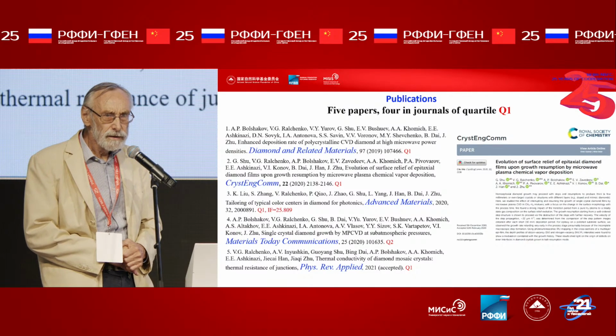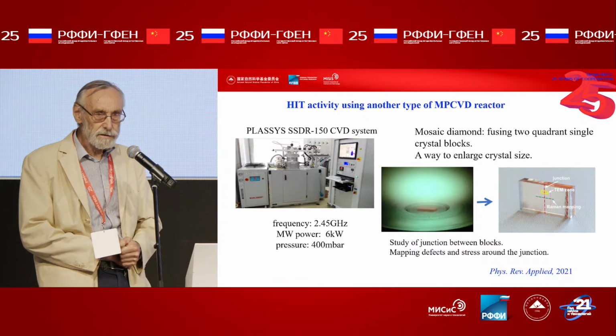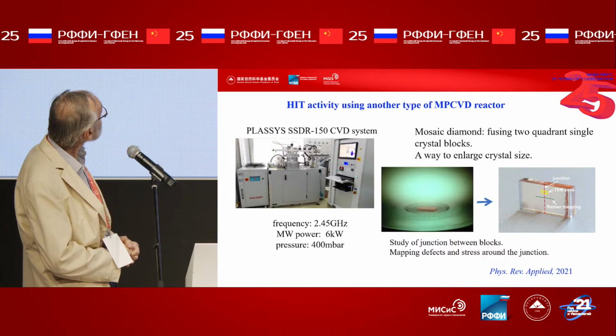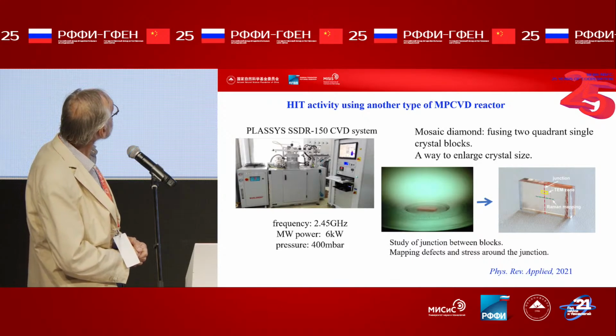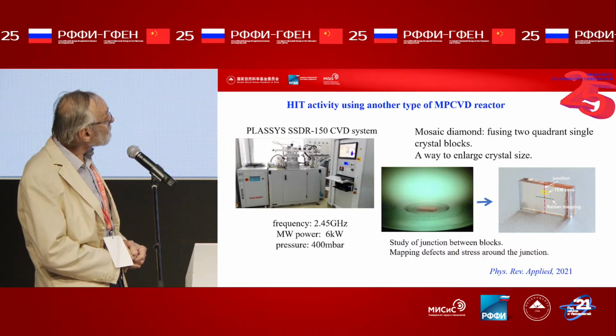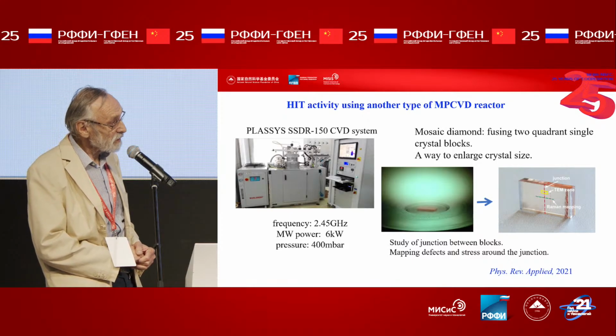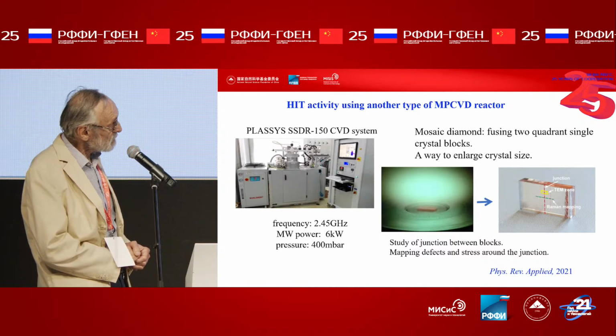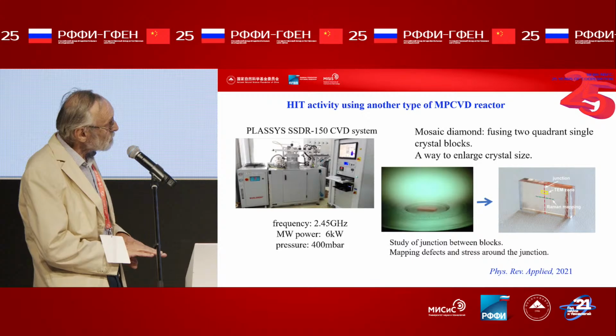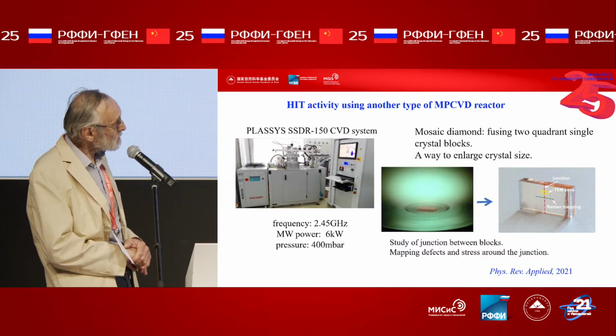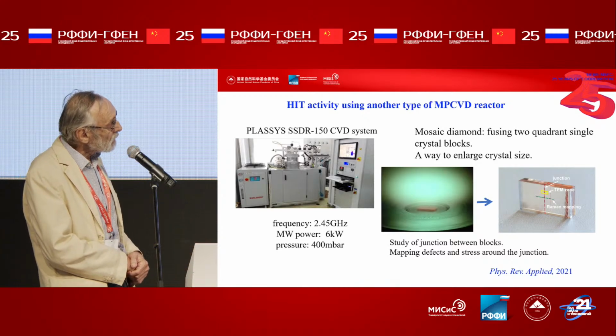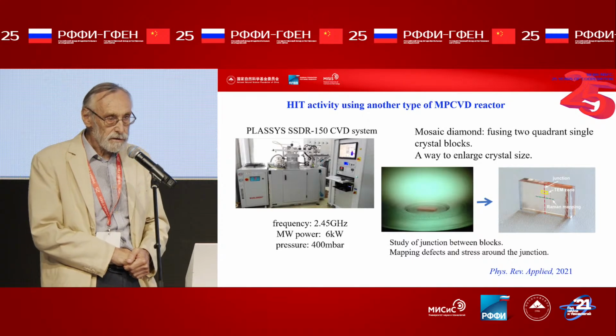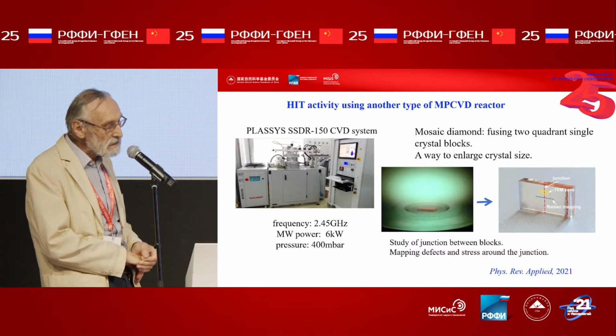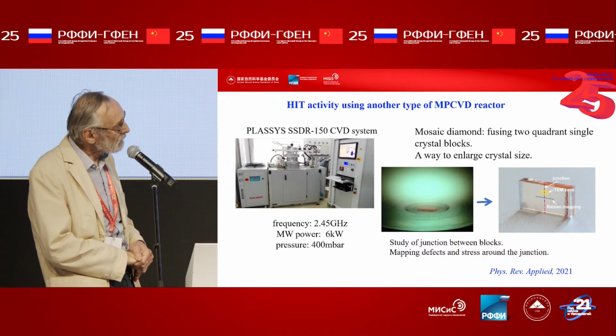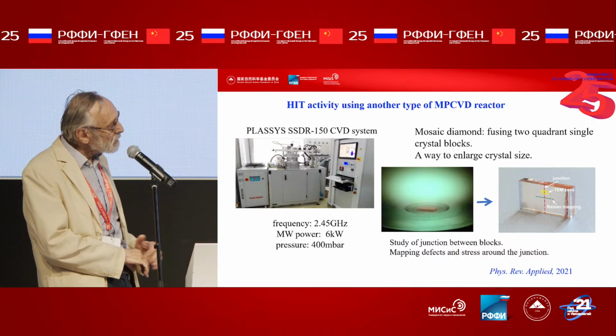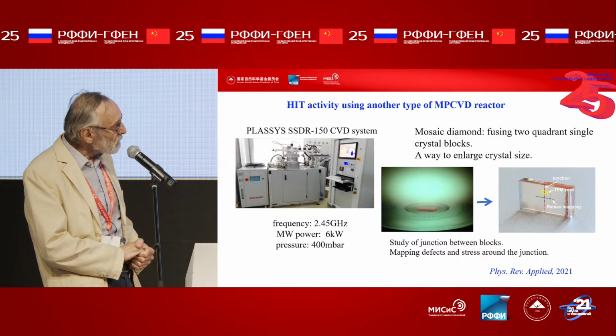Next slide, please. And just two slides from the Harbin group. They use another type of plasma system, a French CVD reactor from Plassys company. An interesting way to increase the size of single crystals is growth of mosaic crystals, when 2 substrates are put close together, and the deposit becomes a single crystal diamond with twice the size. And we examined thoroughly the structure of the interface and found its thickness to be not more than 2 microns. So in fact, the material is a very good single crystal.